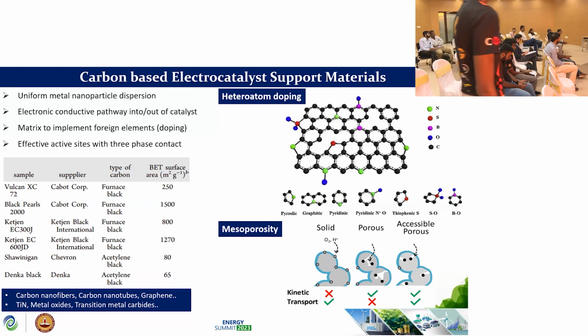Nowadays there are many other types of carbon materials that have been used, like carbon nanofibers, carbon nanotubes, graphene and so on. There are also some non-carbon support materials that have been used, like titanium nitride, metal oxides, transition metal carbides, and so on. We have to effectively increase the specific surface area as well as electrical conductivity. Another important criterion is to introduce mesoporosity into this kind of support material.